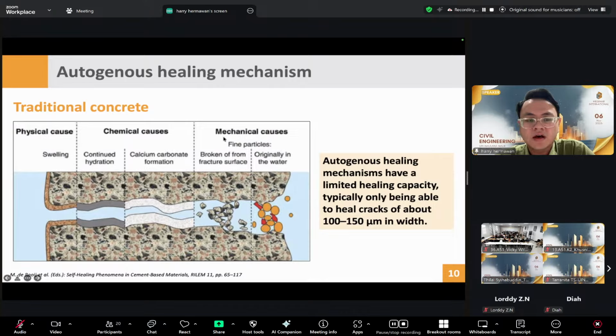Then the third cause for autogenous healing is mechanical. This could be due to the clogging of materials coming into the cracks, either from the broken fracture surface or from the ingress of debris from the water. Regardless of these causes, the autogenous healing mechanism is very limited, healing cracks of only about 100 up to 150 micrometers in width.